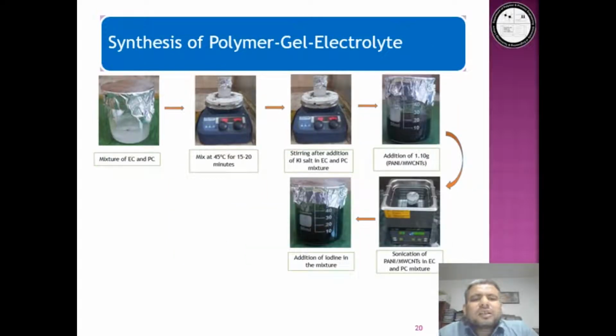Similarly, the next step is how to synthesize the polymer gel electrolytes based on nanocomposite. The synthesized nanocomposite was used as a base material to prepare the polymer electrolyte. In the first step, ethylene carbonate and propylene carbonate were mixed in equal parts at 45 centigrade for 10 minutes with stirring at 300 rpm.